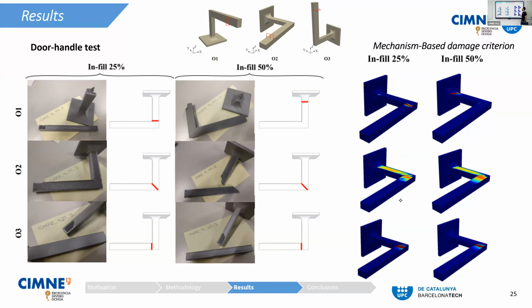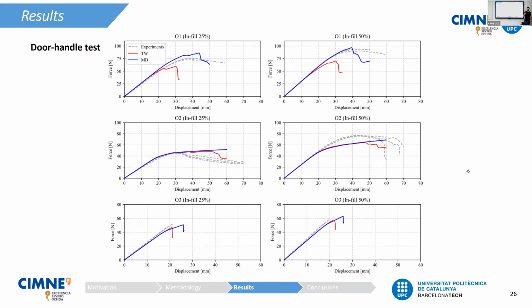However, if we use, instead of the Tsai-Wu, the developed mechanism-based damage criterion, we can see that this special case over here, where the failure occurs at the base, is properly captured with this criterion. Not only that, but also in this orientation 3 result, where the failure is vertical, following the layers' direction, it is again properly captured in these 2 examples using the mechanism-based damage criterion. And of course, the orientation 2 results show the same results as in the Tsai-Wu, which means they break diagonally as the experiments do.